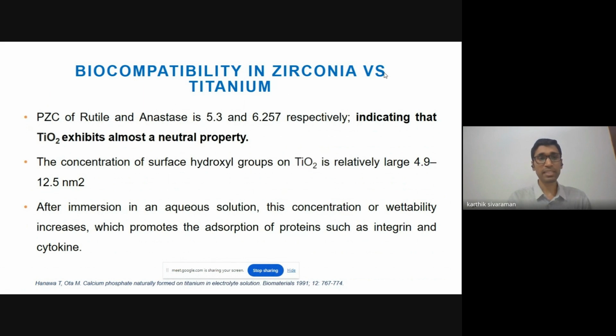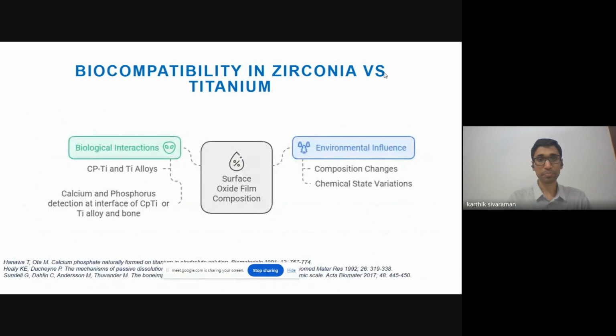When we look at the PZC value for rutile and anatase, which are crystalline phases of titanium, we see that it exhibits almost a neutral property. There is also a large concentration of surface hydroxyl groups seen, which on immersion in aqueous solution increase in concentration and promote the adsorption of proteins such as integrin and cytokines, which are further important for the compatibility with surrounding tissues, especially bone.